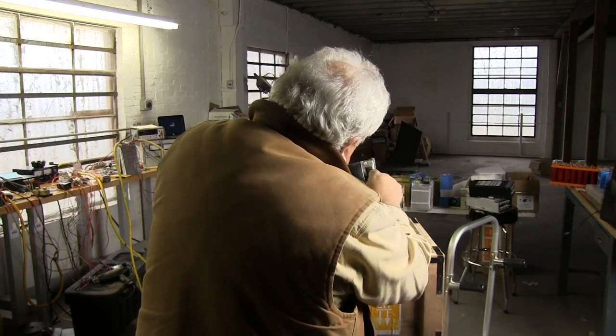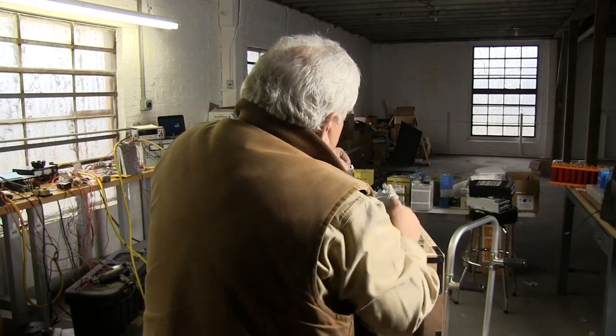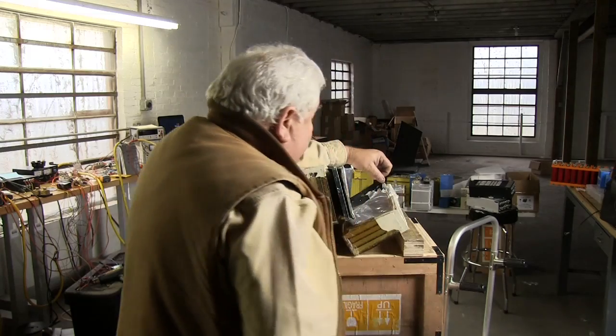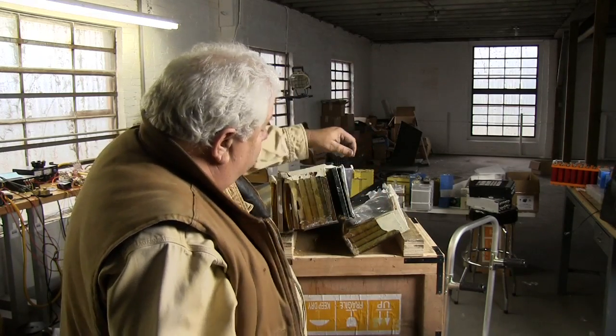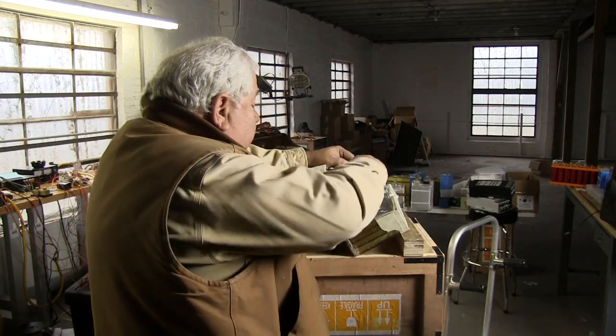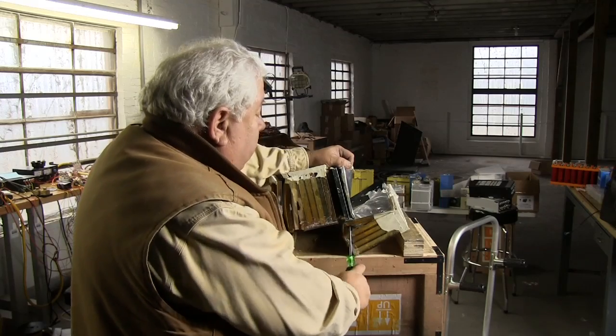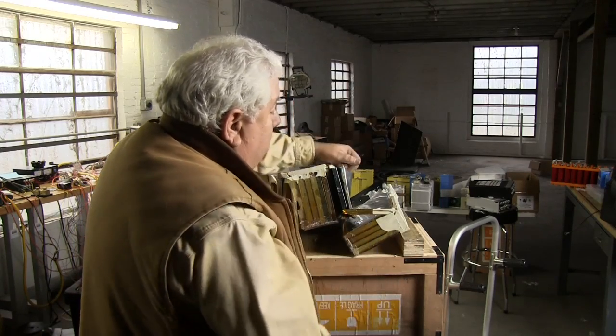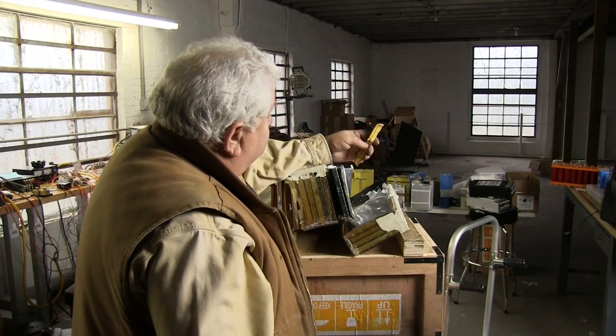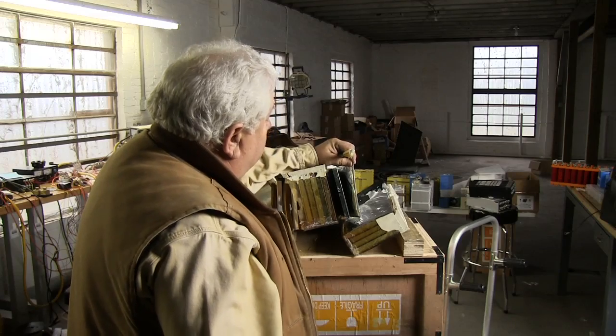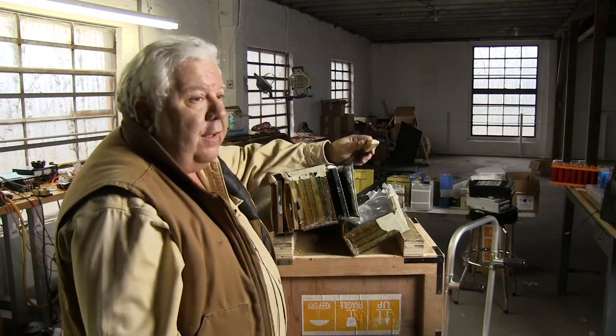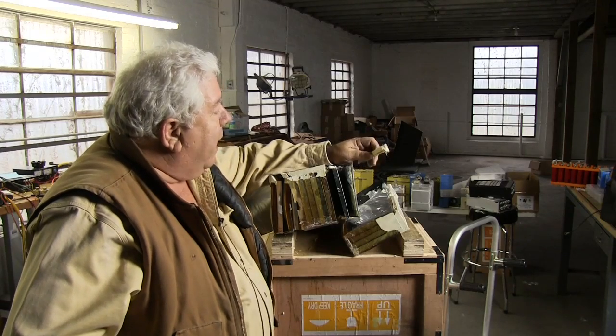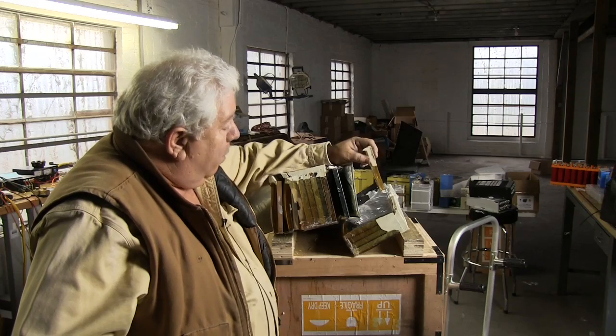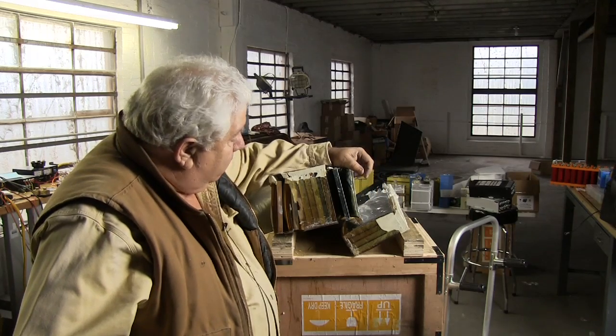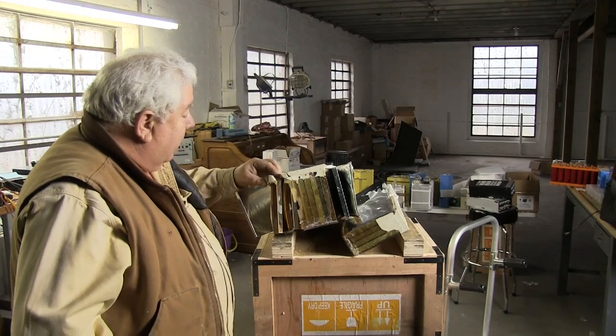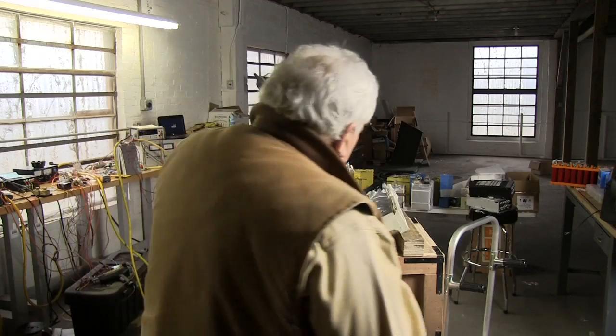They shouldn't normally swell, but this one's swollen, this one's swollen, this one's swollen, so a number of them had decreased in capacity. And I would guess at this point that the 170 degrees exothermic heat of the resin curing process is messing up some of the electrolyte in the cells, reducing their capacity. And had I limited that to a 60 amp hour discharge and put 60 amp hours back in, it might still be okay, but it would not be the pack that we wanted. And if that's going to be the case, we don't want to do that much more.